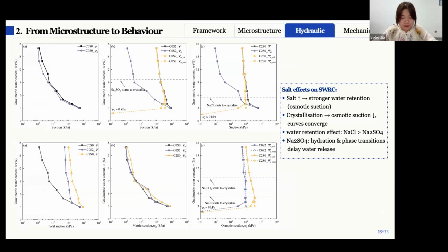So after going through quite a lot of microstructure details, where I have been emphasizing the micro hydro-mechanical coupling, now we can have a look at the water retention behavior. These slides show soil water retention curves under different salt conditions. Overall, we can see that the salt enhances water retention mainly through osmotic suction. However, once crystallization occurs, the osmotic suction decreases and the matric suction curves gradually converge towards the total suction curve.